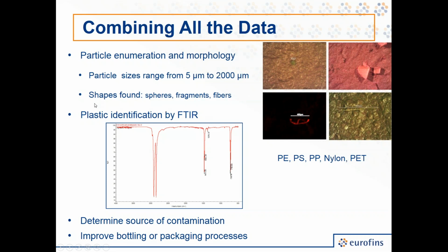Now, typically what we do is we provide information for particles from about 5 micron up to about 2 millimeters. The upper end is pretty easy to change, so we can modify that as needed. Now, the lower end of this scale is dictated by, first off, how accurately can you measure the size, and then how accurately, or how reliably, can you collect spectral data. So size-wise, it's not too difficult to make measurements at the 5 micron size with an ordinary microscope, but with an FTIR system, it is very difficult to get chemical information at this small size.